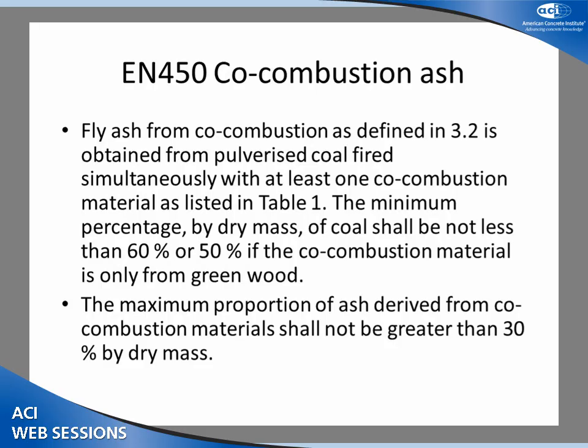But the other interesting thing, which I didn't mention earlier, is that the CSA standard allows co-combustion of up to 25% pet coke with the coal ash, because a lot of plants are burning pet coke in combination with coal, so we actually allow it in the spec. I think ASTM C618 is a little quiet on the situation. But EN 450 allows co-combustion as well in their standard, at least the latest version. They limit the amount of co-combustion material to about 30% of the ash composition.